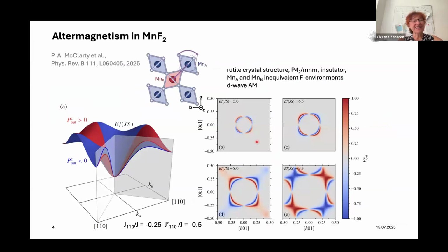Right. In the same article, they used manganese fluoride to show what happens to the magnons because of altermagnetism. And this is a classical material. Besides magnetic order, you have the moments oscillating in a long-range fashion, and you would have spin waves, which in specific directions, the diagonals 1, 1, 0 and 1, minus 1, 0, show a split of otherwise degenerate modes.